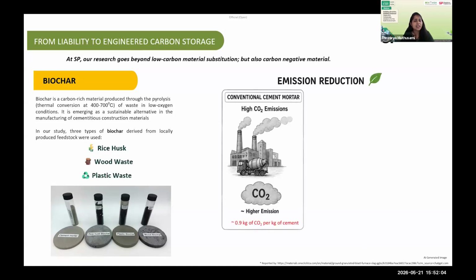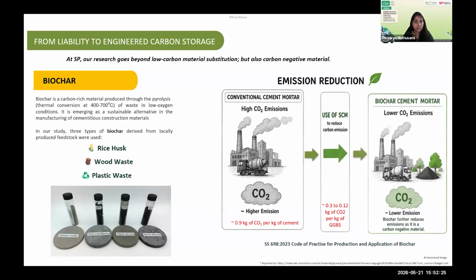In general, what is usually done for mortars is that it has cement content. And no doubt it has a very high carbon emission number. Traditionally, we look at SCMs. We try to reduce the amount of cement that is used there because these SCMs have a much lower carbon emitting number. Now we are going beyond that. Can we use materials that contribute much lesser than just the use of SCMs? Can we use biochar? Because biochar, especially the biochars coming from the biomass sources, have sequestration potential, making it a carbon negative material for use. And that helps us with a lot of other Singapore goals that have been set in the market.